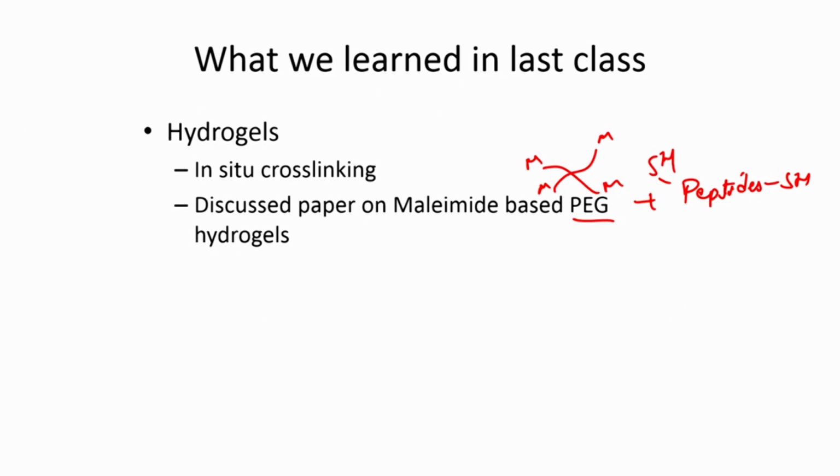And what we found was basically there were several chemistries that can lead to the production of the hydrogels, but among the 4-5 moieties that this group had compared, they found that maleimide was by far the most efficient as well as well suited for any in situ applications, because the gel was then able to cross link and then adhere to the tissue as well.